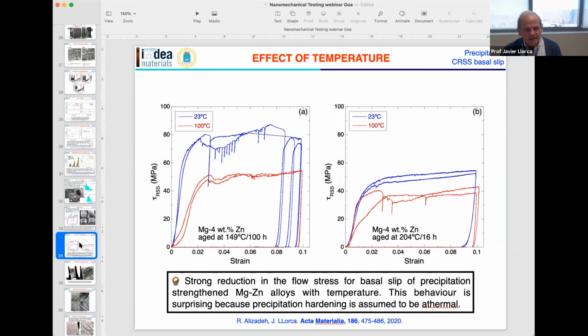We also did tests at different temperatures. These are for 2 different aging treatments. This is the peak age condition. This is the overage condition. The blue are the resolved shear stress versus strain curves at room temperature, and the red ones are at 100 degrees Celsius. One thing that is interesting here is that when you increase the temperature a little bit, from 23 to 100 degrees Celsius, there is a huge reduction in the critical resolved shear stress.